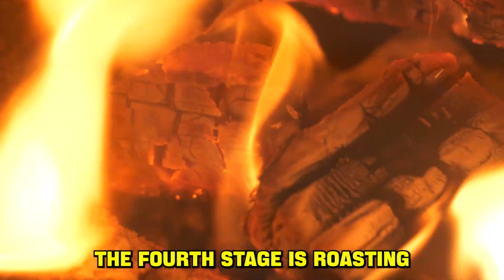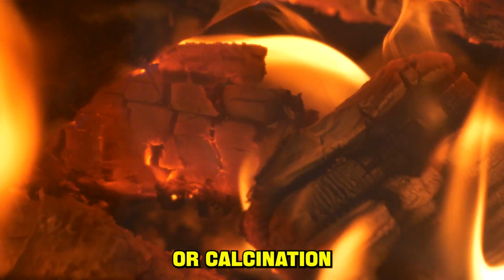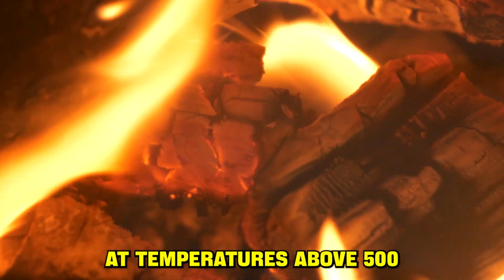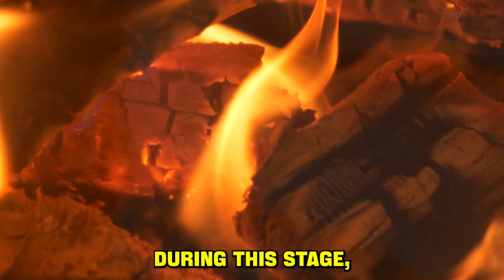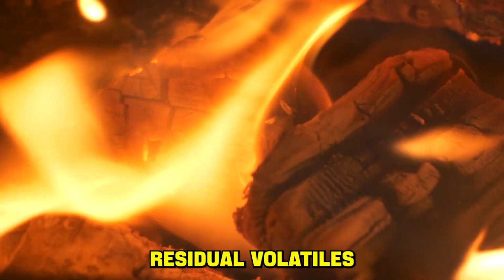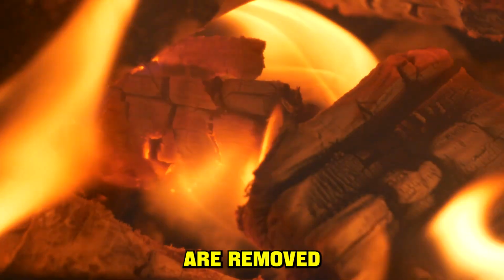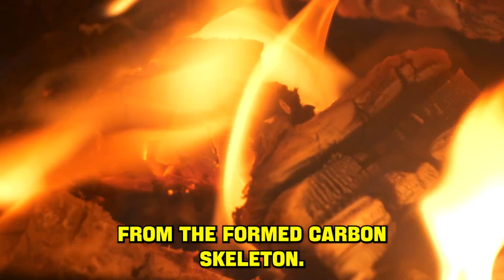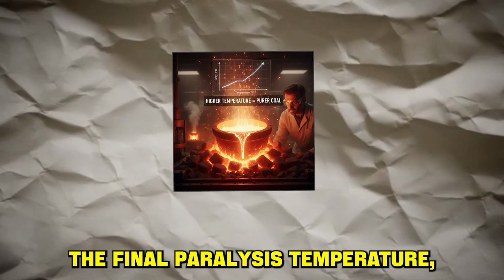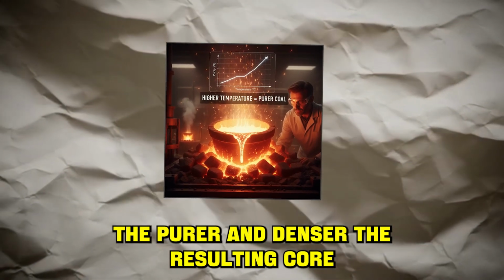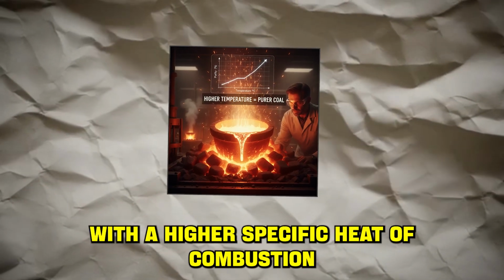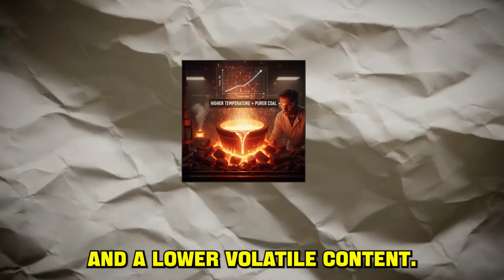The fourth stage is roasting, or calcination, at temperatures above 500 degrees Celsius. During this stage, residual volatiles and resins are removed from the formed carbon skeleton. The higher the final pyrolysis temperature, the purer and denser the resulting coal, with a higher specific heat of combustion and a lower volatile content.